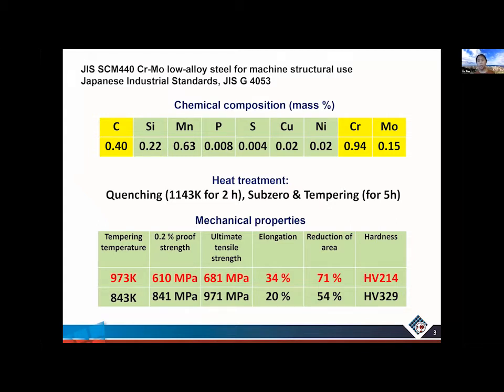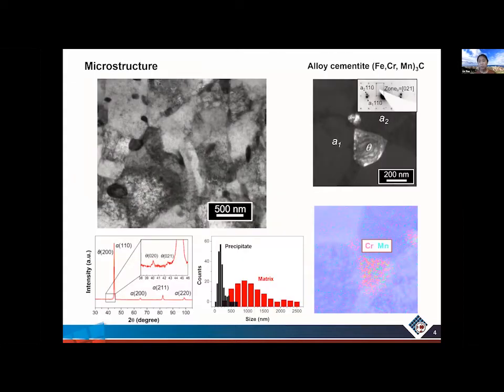The reason that we choose a more ductile material is hoping to see a more significant change when hydrogen embrittlement occurs. And the microstructure of the material consists of a ferrite matrix with a grain size of about 1 micron and with some cementite precipitates in it.